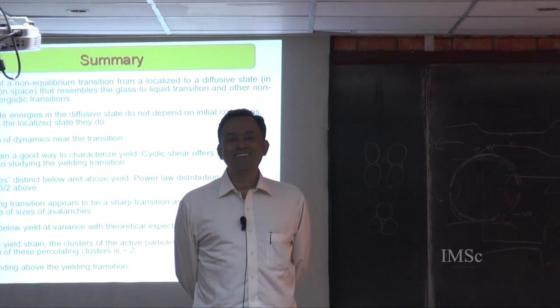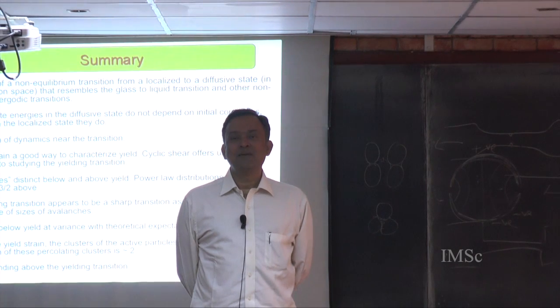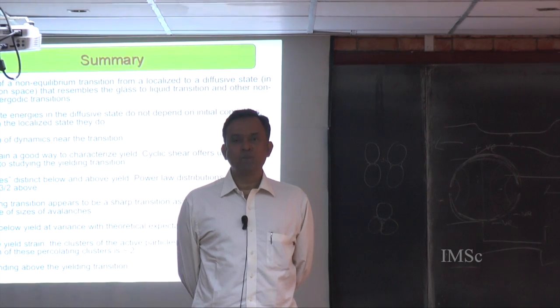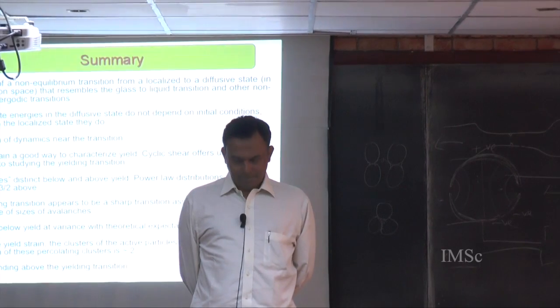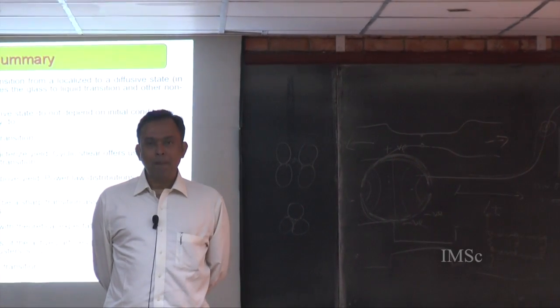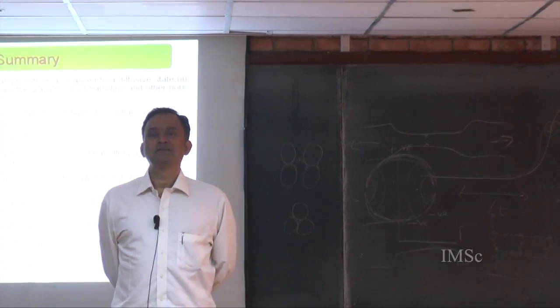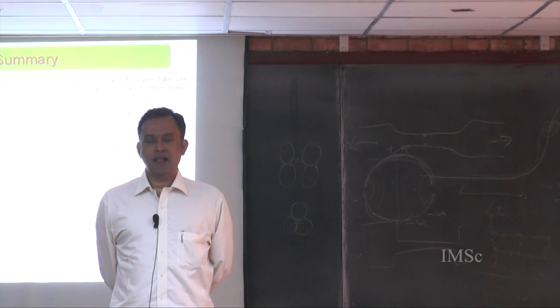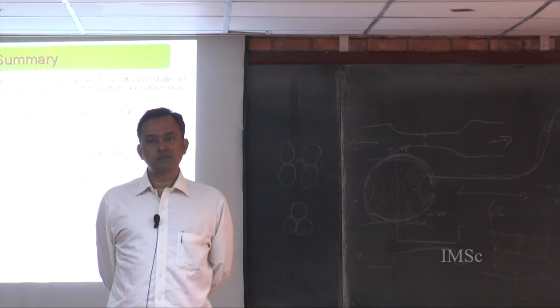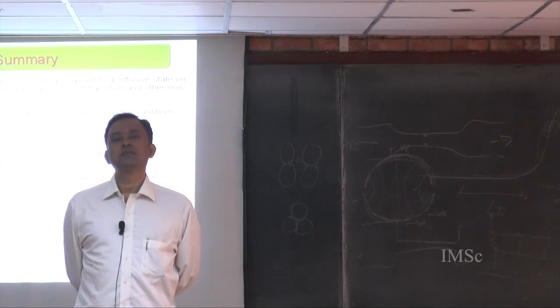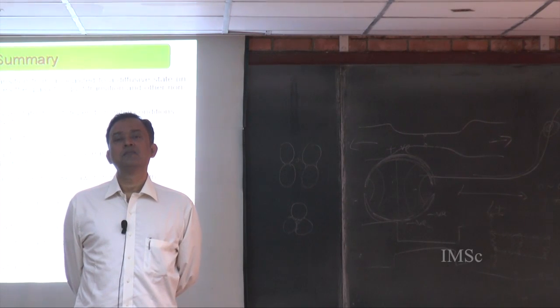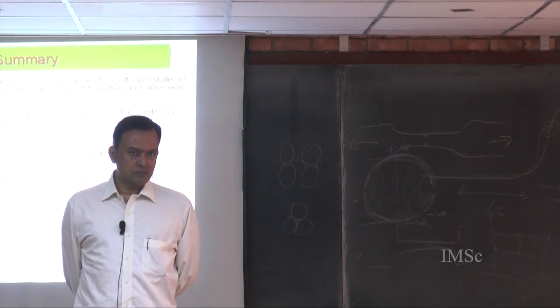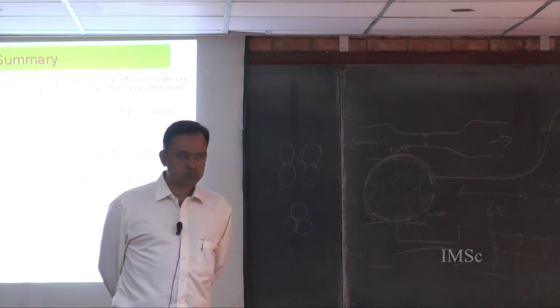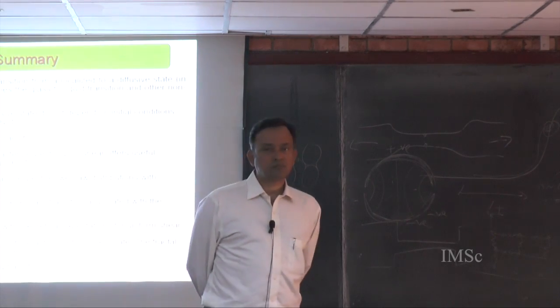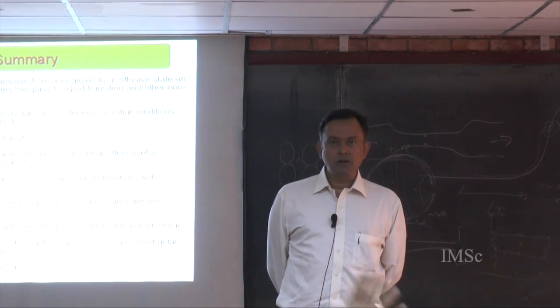You showed that the minimum in the energy plot happens at zero strain till you reach a critical level. So just to understand it from a mechanics standpoint, if you do loading and unloading, once it yields, you will have residual strain. Is that the strain at which the minimum is reached? So the relaxed state would be the minimum in the energy once you go beyond the critical, because it shifts out, right? You get more and more residual strain.